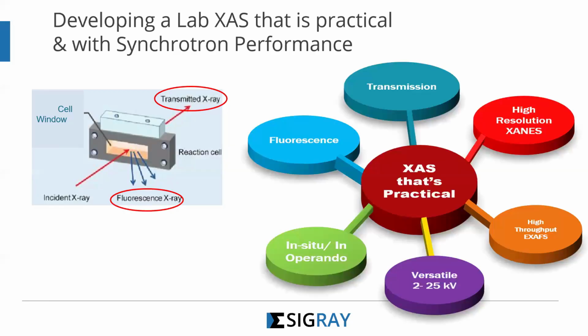So therefore, if we were to summarize this, a practical XAS tool must have the transmission mode and the fluorescence. Why transmission and the fluorescence? If you have a lot of pure samples, more than 5%, transmission will be okay. But what if you have less than 5% of the material of interest? Or what if your sample is dilute, you're working with a thin film, like in semiconductors, or you're working in the liquid, then you have no choice but to run it under fluorescence mode. That's what they do in the synchrotron.